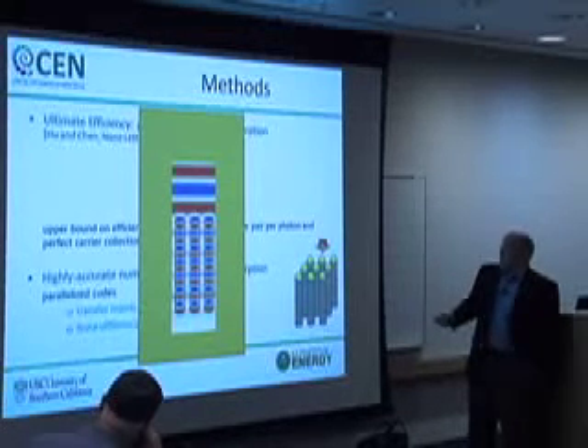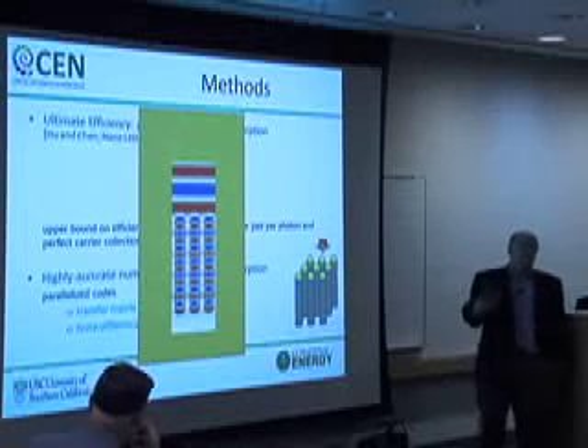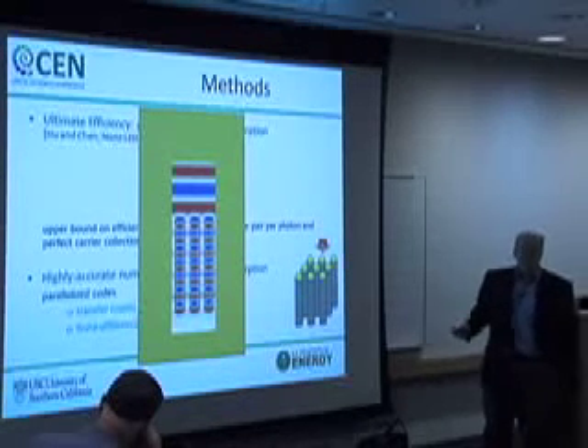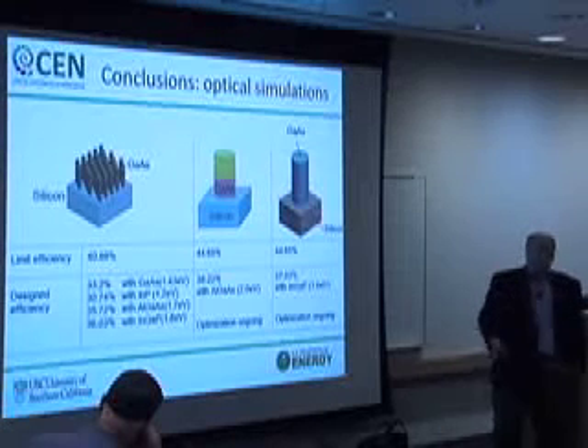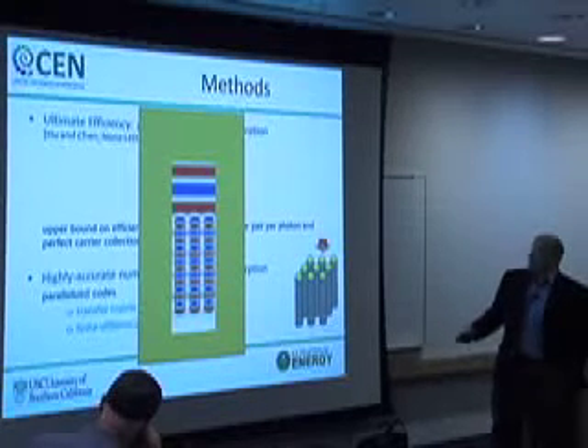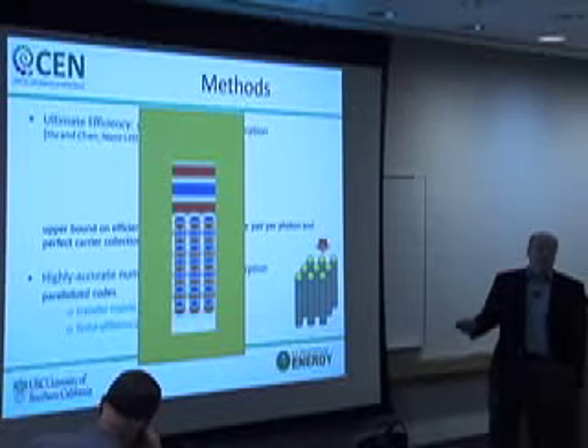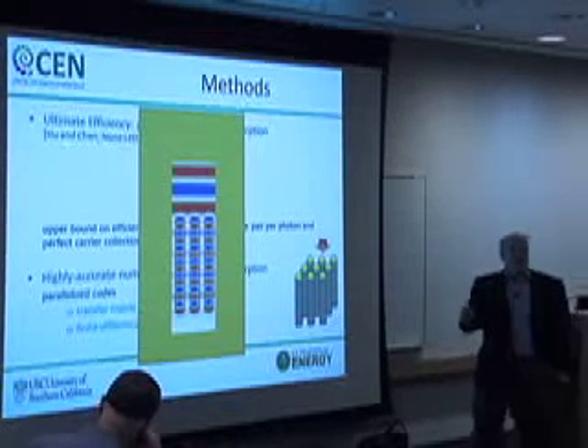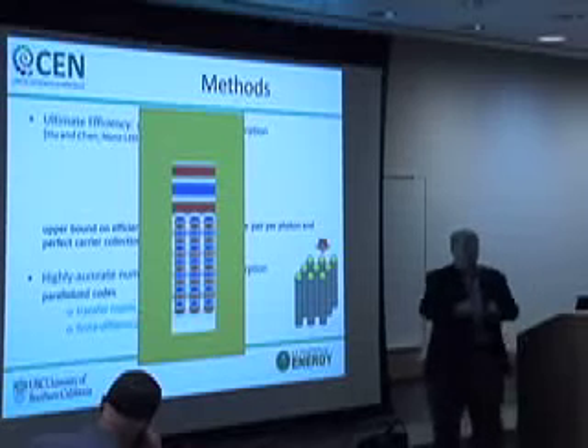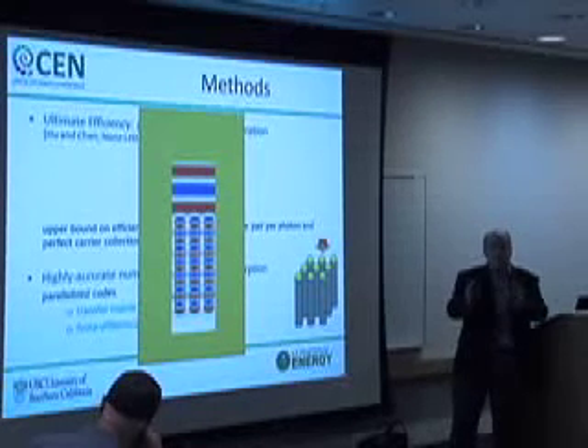So one of the first conclusions that we reached is that, in fact, even though the surface might be sparsely covered by these nanorods, because of the high index of these materials compared to the surrounding air, light tends to be concentrated in the nanorod. So, for example, if you have only 10% of the area covered, you get roughly a factor of 10 concentration of the light within the dielectric medium. And that has certain advantages because that means that the current per unit area generated in these structures will be 10 times higher, and you get some of the advantages of concentration, although modest concentration, by using this kind of structure.